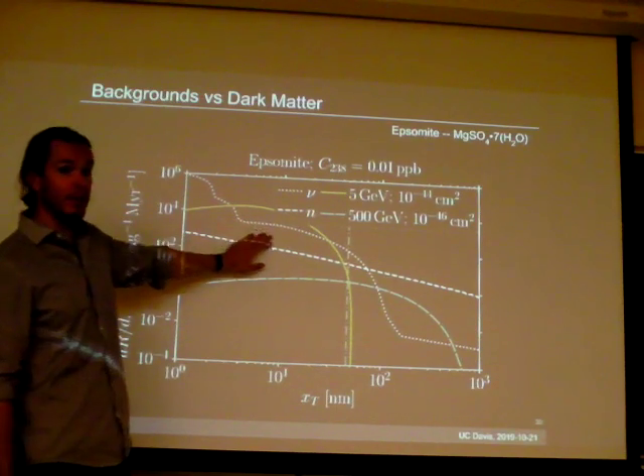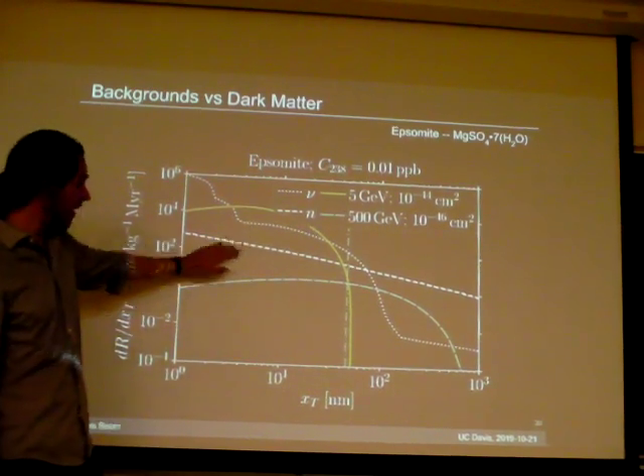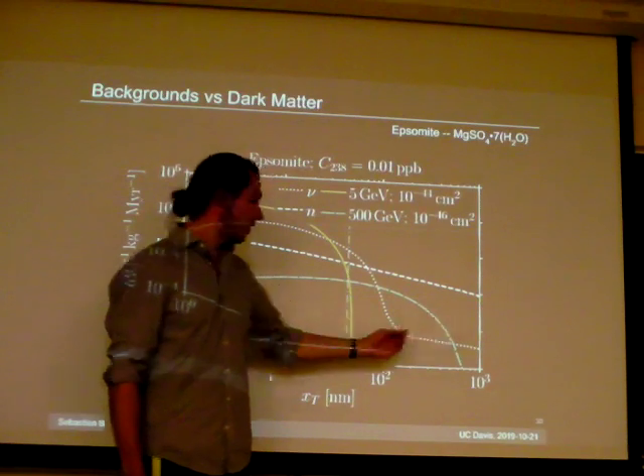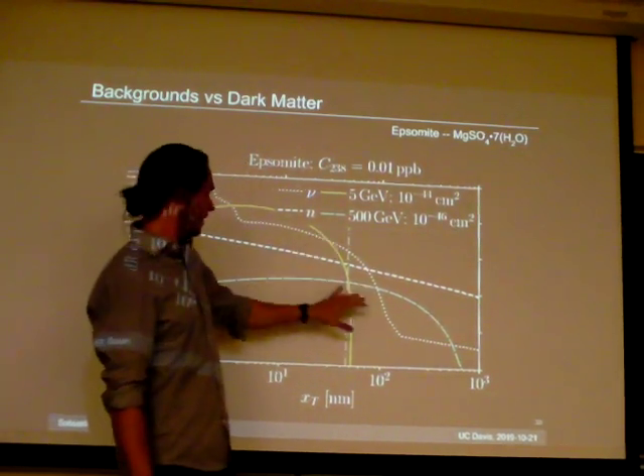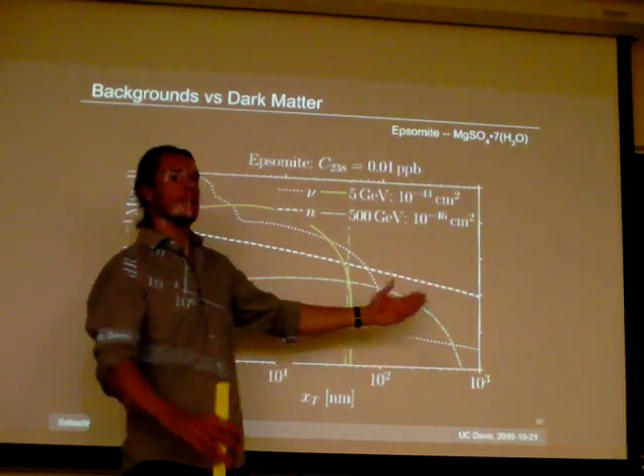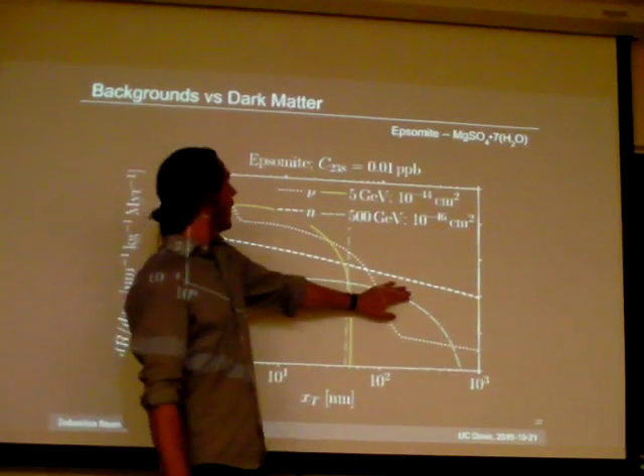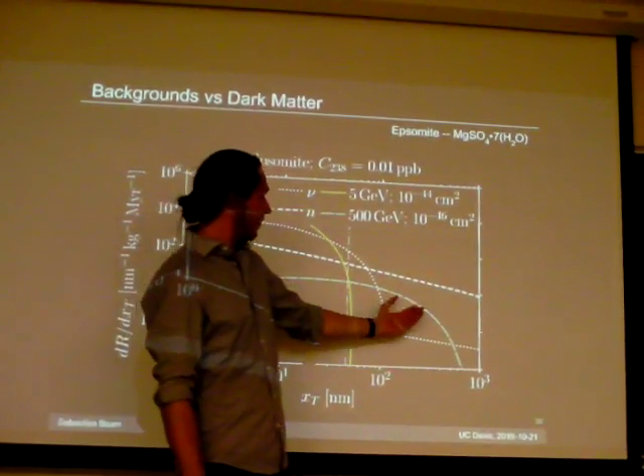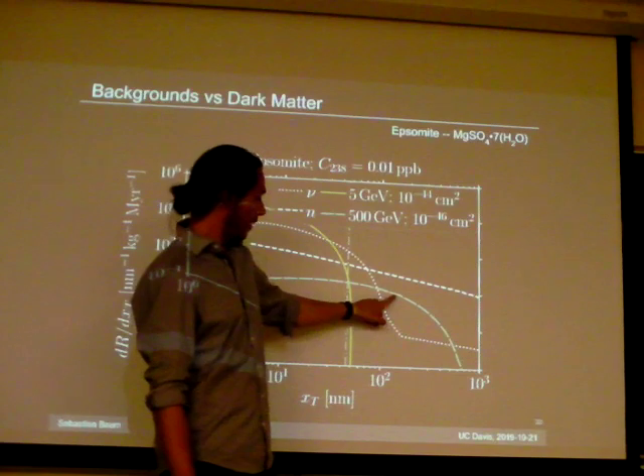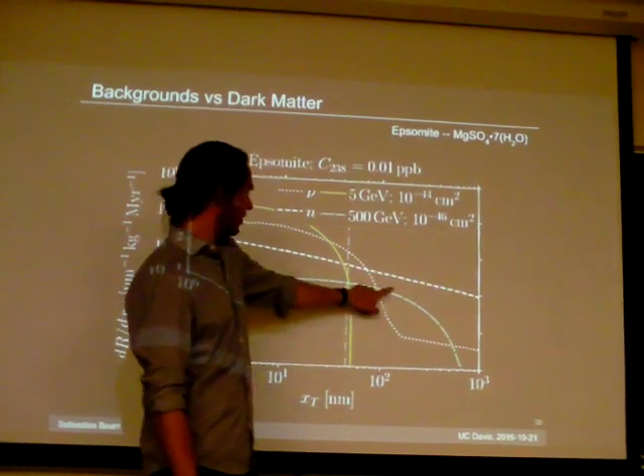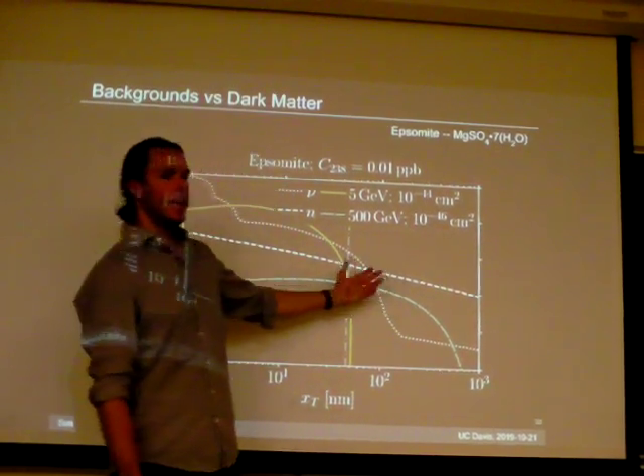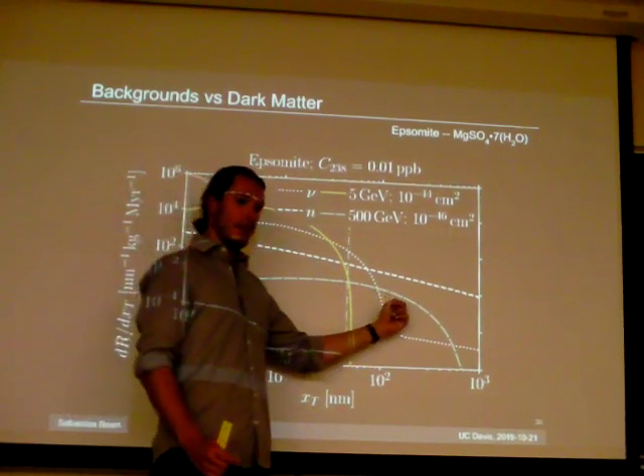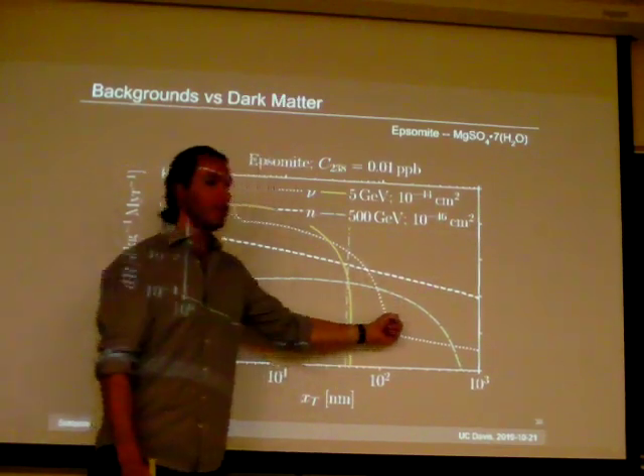Your dominant background is going to be neutrinos. If you look for heavier dark matter, honestly, these look very similar once you go above something like 15 or 20 GeV or so. If you look for something above that, some heavier WIMP, you want to look at longer tracks, right? Your best signal-to-noise ratio is going to be somewhere here, 100 nanometers or so. So you don't need as good spatial resolution, but now your dominant background is limited not by the neutrinos anymore, but by the neutrons, right?